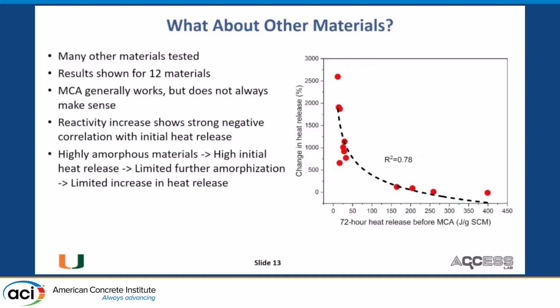Okay, one material is fantastic. What about others? We've actually tested a lot of other materials, and so have others. I only show here the results for 12 materials. So MCA generally works with some caveats. Meaning, what we see is that if you plot the increase in reactivity versus the initial reactivity, you see this kind of exponential relationship. The exact relationship is not so important, but basically what you see is that when you take materials which are very reactive, you don't really do anything to them.